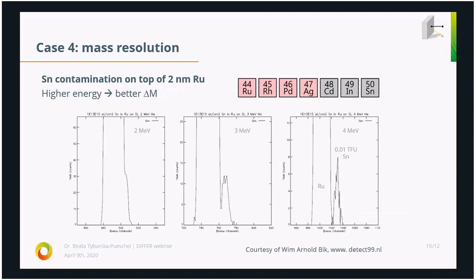The general problem with the Singletron, as I told you, is that we can use a maximum of 4 MeV beams. So in our case, there is some limit to the mass resolution of what we can do for you, because simply we cannot go to higher energies than that. But if some of you have samples with elements of similar masses, then just come to me. I can perform simulations for you before starting measurements, and I can tell you whether it would be possible to distinguish those masses or not.